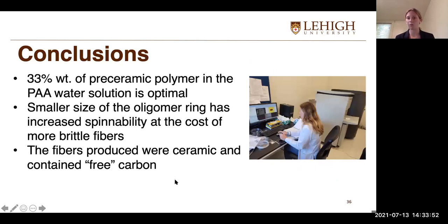My conclusions overall from this project were that the 33% weight of the preceramic polymer in the PAA water solution is the optimal ratio. That was what gave me the best fibers. Additionally, the smaller size of the oligomer ring has an increased spinnability at the cost of more brittle fibers. So I was actually able to spin fibers at a higher ratio, but they turned out way more brittle and not very great. And finally, the fibers that were produced were ceramic and they contained free carbon. So that was another thing that we weren't sure about since this preceramic oligomer has not been studied before.